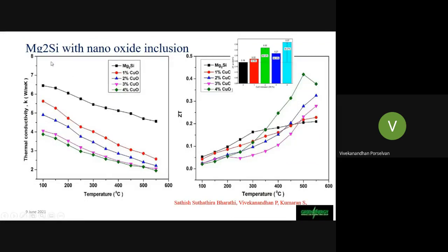And another approach is a nanostructured magnesium silicide that is included with nano oxide inclusion, where we can see the drastic reduction in the thermal conductivity, and we can see that the ZT can be increased up to 0.37, which is very large as compared to the pristine or pure Mg2Si, which has a ZT of around 0.19. Whereas Mg2Si doped with oxide inclusion at a higher concentration, that is 4% of CuO, shows the high 0.37, which is an increase of around twofold.